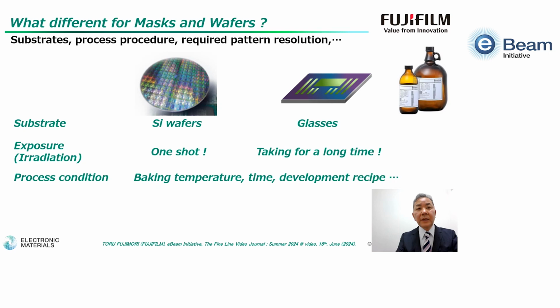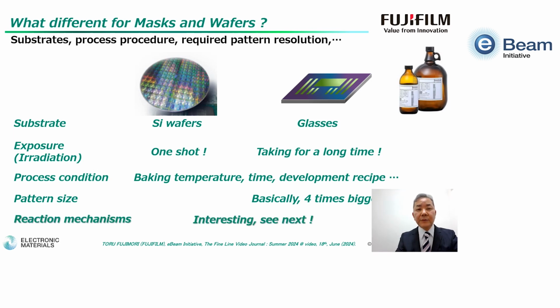Process conditions, baking temperature, time, recipe, and pressure are a little bit different. And also the panel size for masks is basically 4 times bigger than the wafers, but the sub-pattern needs to be prepared with small feature size, the same as the wafers. And the reaction mechanism, this is very interesting. See the next page to show more detail.